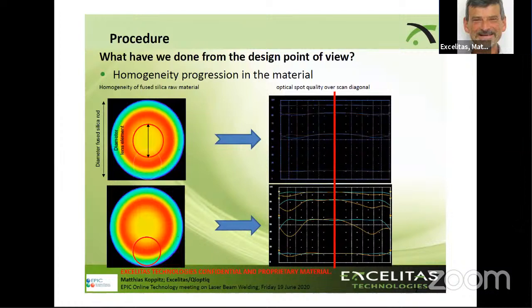What was very important and surprising was the homogeneity progression of the different fused silica materials. You see on the left side a cut of the fused silica rod, the raw material, and you see the different homogeneity in the cross section. When we cut the raw diameter for a lens element, you see you have different propagation over the diameter.